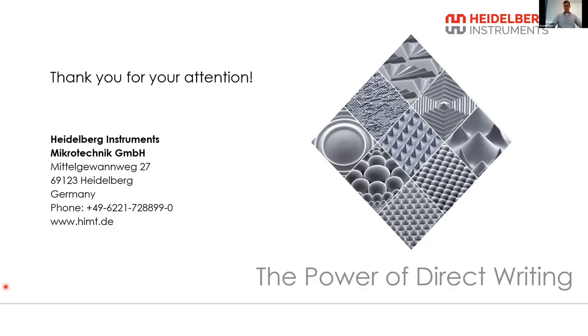We were basically exposing the photoresist like you would do with a mask aligner. So we are supplying basically the same amount of energy. We just do it very fast. The laser pulses that we use are in the nanosecond, or depending on the system, microsecond range. But the powers that we use for the exposure create no heating effects. We also have tested this for some customers that had the same concerns because they were working on sensors where the material would be sensitive to these possible heat changes. And there was no effect, basically. It is, of course, possible with the laser to increase the power to a level where you can damage the resist or even the substrate. You can burn it if you want to, but for standard exposure, there's no thermal problem.